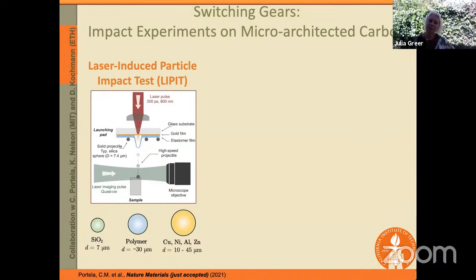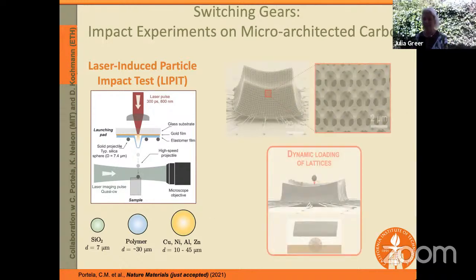Okay, so let's switch gears a little bit and let's look at the same micro and nano architected carbon. Instead of quasi-statically deforming it fully, like I've been showing you up to this point, let's impact it at maybe hypersonic velocity. So for that, we collaborated with a lab at MIT who developed this technique called Laser-Induced Particle Impact Test, or LIPIT. The idea is that you have a laser pulse during which you accelerate these particles that are on the order of 10 to 40 microns in diameter, and you're able to document it and to image it as this is happening.